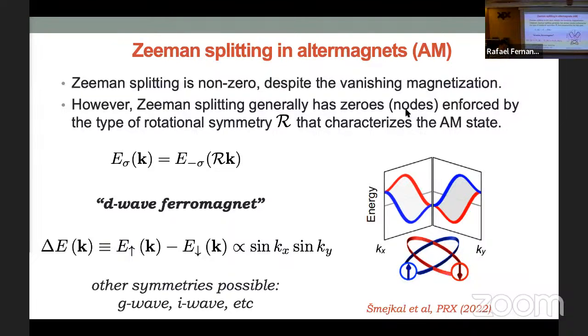The name can be helpful or also not helpful, depending on your point of view, because it's not really a ferromagnet. There's no magnetization. But the d-wave here is just to remind you that the spin splitting has a d-wave form factor. Okay? So this example that I'm showing here is a d-wave ferromagnet, but it could be g-wave, i-wave, any, even in momentum. Okay? And I didn't mention that, but this idea was very nicely articulated and proposed in this paper by Libor Šmejkal, Jairo Sinova, and Tomas, explaining the symmetry operations here.